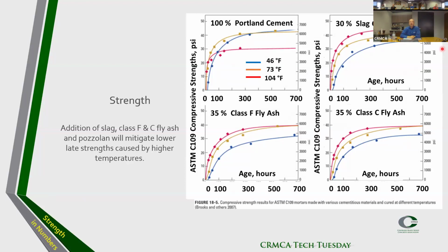This graph shows SCM, supplementary cementitious materials. Upper left is just a pure Portland cement. They were cured at 46, 73, and 104. And you see that the one at 104 takes off very nicely and then tapers off again. I'm not sure why they put in there the H in hours, but that's like 700 hours. It's more or less 28-day strength. But you see that the 46 and 73, they gain momentum later on, and they keep on going.